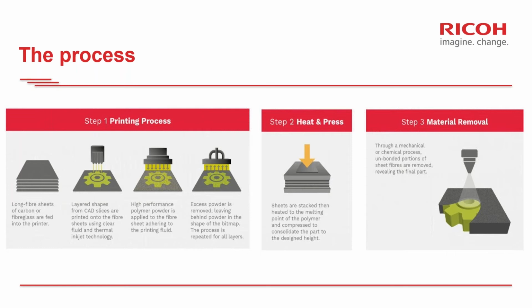And the second phase is the heat and press. Once all of the layers are in place, the part is heated to the melting point of the polymer under a specific load. The particles melt and encase the fibers to fuse the layers together into a solid component. We then have the third phase, which is the material removal. As a final step, the unbonded portions of the fiber sheets are blasted away, revealing the geometry of the final component. Unlike chopped fiber parts, the resulting part is end-to-end reinforced with long fibers, providing an improved level of strength.